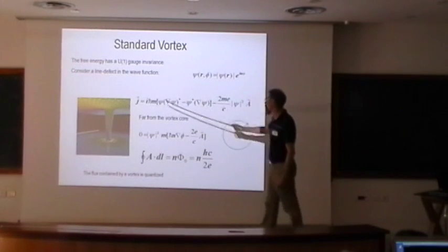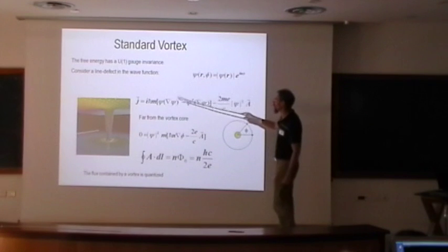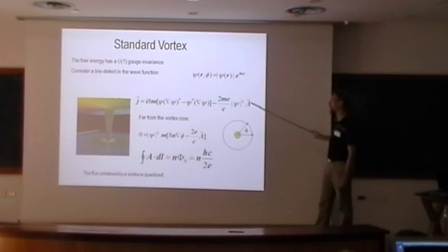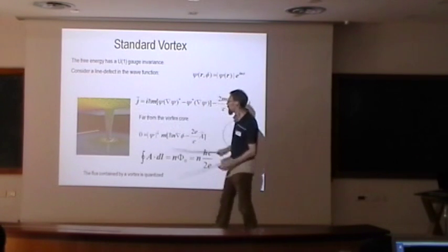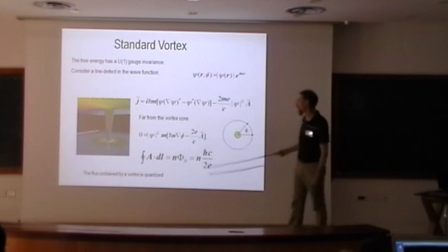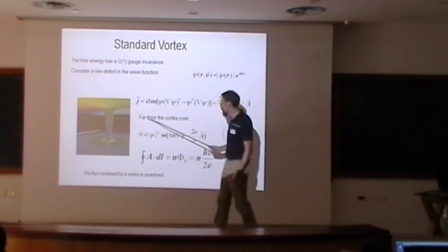And the current is just a quantum mechanical current. And so what I've done here is I've allowed gradients of this order parameter to show up, but I've also now included a vector potential because we have a superconductor. Now, very far from any vortex core, so here's your vortex core, pushing the order parameter to 0, but far away it's approximately constant in magnitude. Very far from the vortex core, the current must be 0.